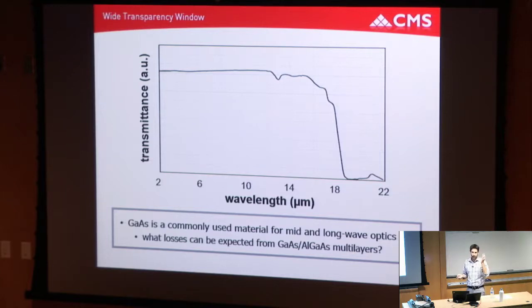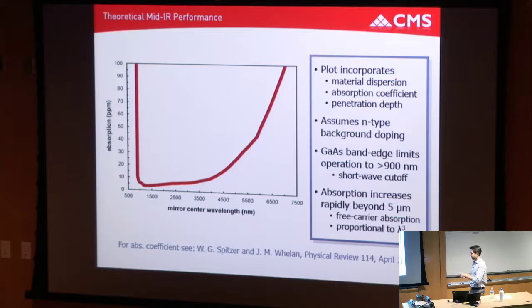But that transparency window is wide. But then the question is, this is percent level, so how low are the optical losses in the system in reality when you're looking at PPM levels of losses? So a couple years ago, I did a quick theoretical exercise. So this is absorption as a function of various mirror designs. A bunch of quarter-wave mirror structures that are interpolated together to make the total mirror loss in absorption.